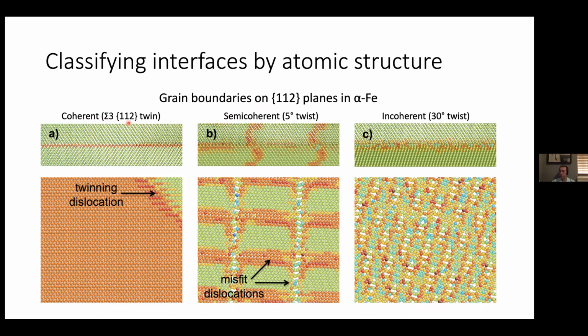Alpha iron is a BCC, body-centered cubic material. This coherent sigma-3 twin boundary has a boundary plane along 112 type facets in both of the two neighboring grains. This top figure shows you a view of that boundary looking edge on, right? So this sort of region right here is the actual grain boundary plane.